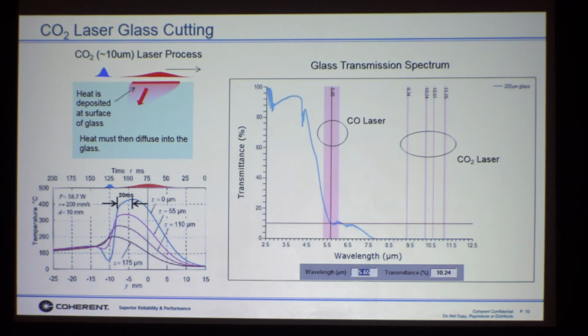What's very important is not to add too much heat into the glass. That's always been a problem with CO2 because it's kind of non-intuitive. If you look at this transmission spectrum, CO2, and these lines here all represent CO2 transitions, are 100% absorbed by the glass. So when you put CO2 light down on a glass, you get penetration between 3 and 8 microns. Everything is absorbed by the surface. Extremely strong absorption. So what people typically do when they're cutting glass with CO2 is they'll elongate the beam. They'll stretch the beam out along the cutting path in order to distribute the heat.